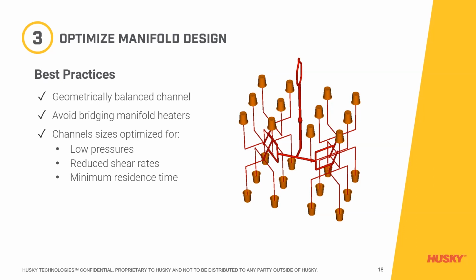This should include geometrically balanced channels. Basically, the distance from the sprue bushing to each gate or to each part, whether it's a 2-drop or 144-drop system or 144 cavity system, we want to make sure that that channel length is the same, and that's what we refer to as geometrically balanced. Avoid bridging manifold heaters. Typically hot runner suppliers will have a heater on the injection side and another heater on the clamp side of the manifold. Many times we will bridge those heaters or connect those heaters together to have one thermocouple controlling both of those heaters. We would recommend not doing that to give you better control of the thermals of the manifold.